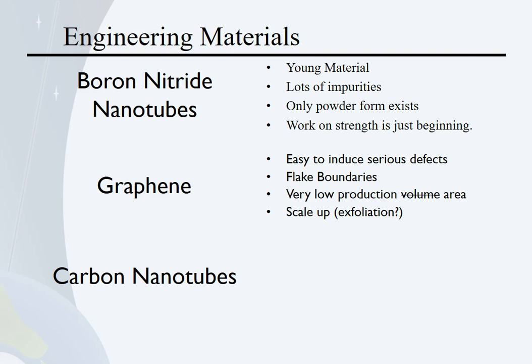We've also got issues with the flake boundaries. If we just stack graphene on top of each other, we get graphite, pencil lead, not known for its high tensile strength. If we try and bind the graphene together at the flake edges, better, but now we've got a polycrystalline material. If we try and synthesize large quantities of graphene, the best approach is to do an area-based synthesis, where we take a big sheet of copper or nickel, load the surface with carbon at a high temperature, and then let that carbon crystallize out into graphene.